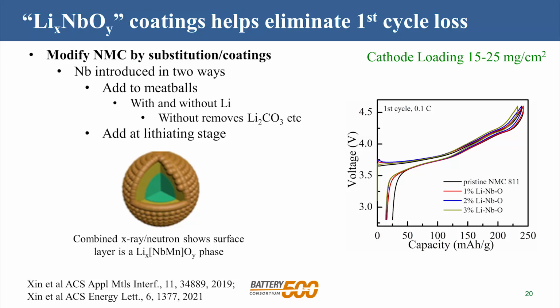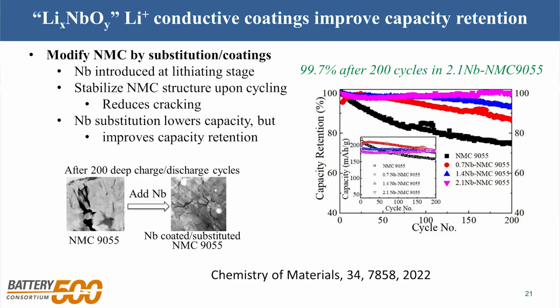And you can see from the curve on the right, we've now reduced this first cycle loss by 50% with just 1% niobium in the material. And this is basically stabilizing the material and also allowing the lithium ions to transfer much more readily. So we looked at this a bit harder, and our colleagues at DOE said, you can't have this extra heating step. This is going to cost too much. So we said, well, we'll add the niobium at the same time we add the lithium. And this is what we did.